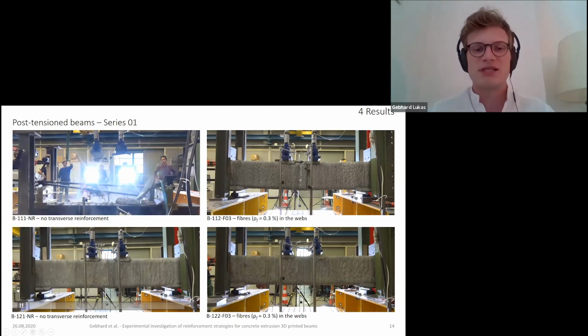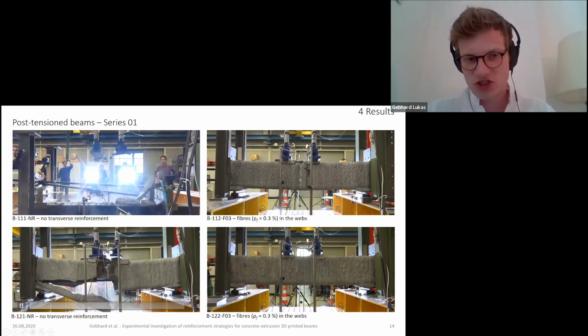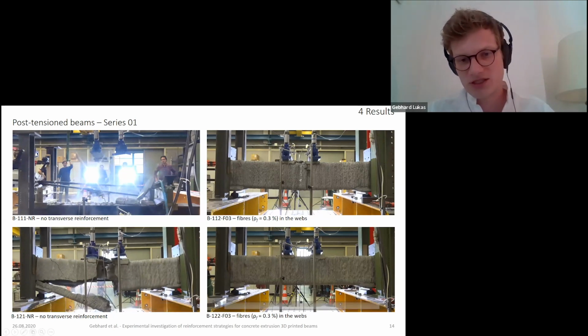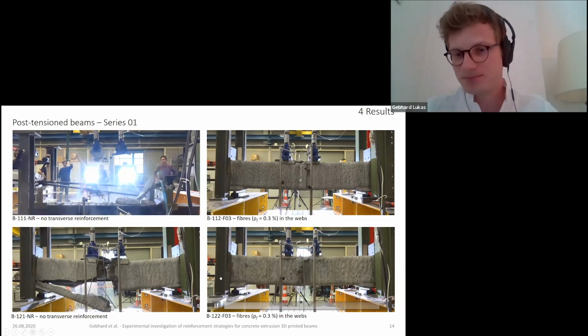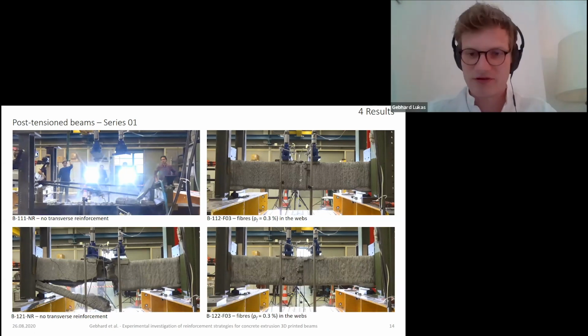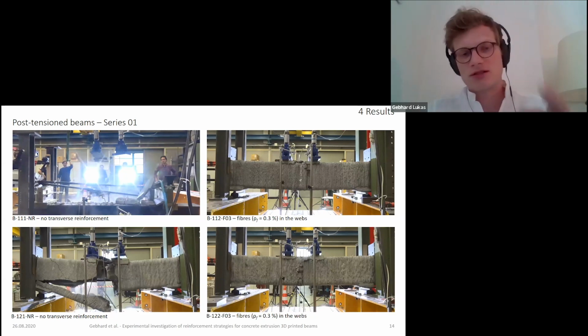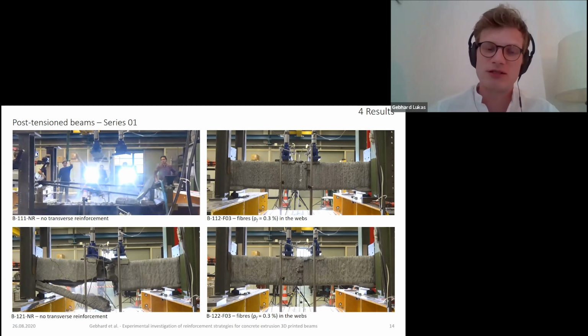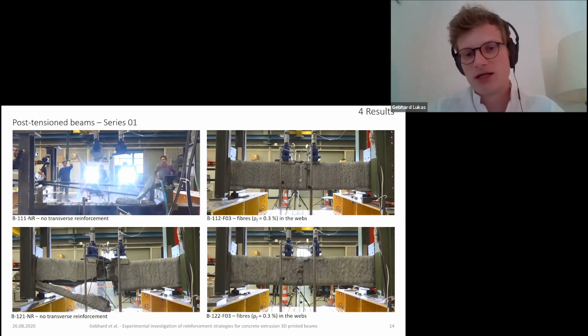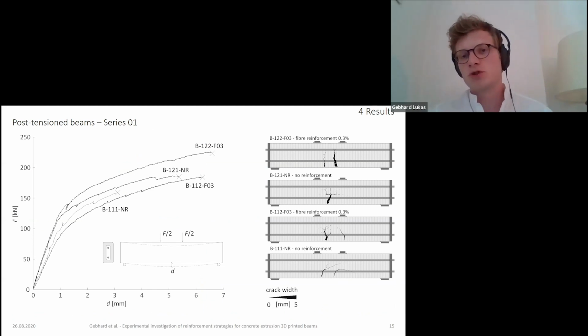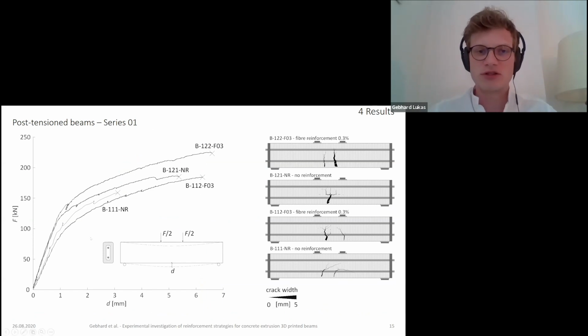And the same could be seen for the series with the different post-tensioning, where we had a total collapse of the structure without reinforcement and bending failure for when fibers were present. Just to mention, this is the backside of the beam, so we do not see the digital image correlation surfaces here. But we use this digital image correlation surface to produce these crack patterns here on the right. And on the left, you see the load deformation curves.